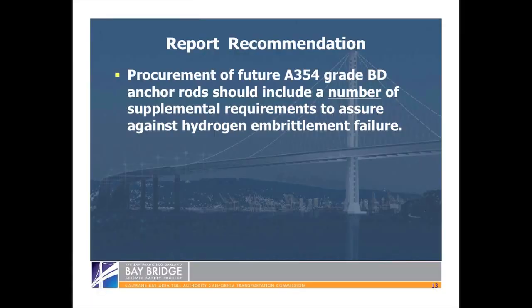The combination of all these factors have caused the anchor rods to be susceptible to hydrogen embrittlement, which ultimately was the cause of their failure. The recommendation is that future procurement of A354 grade BD anchor rods should include a number of standard supplemental requirements to assure against hydrogen embrittlement failure. The appropriate specification of supplemental requirements is currently under review, and I think we'll talk about that a little bit later on as what we're doing with the 2010 bolts, such that it will lead us to potentially modify the amount of testing we do on this type of bolt going forward.